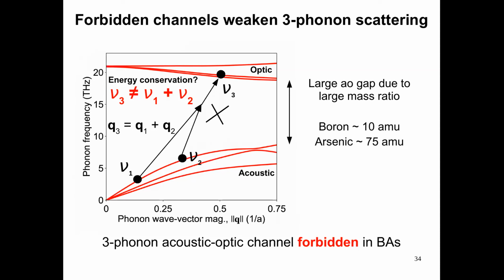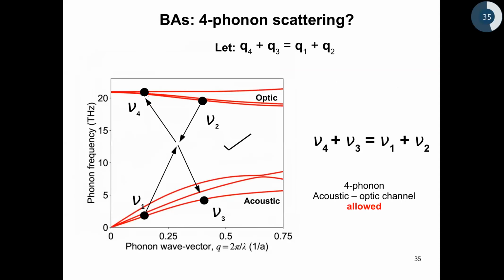So naturally, a question will arise at this point: what about higher order scattering involving more than 3 phonons? So clearly, you can see from this picture that if you add 1 more phonon to the mix, you can satisfy both momentum and energy conservation simultaneously. So at least from the constraints perspective, 4 phonons acoustic optic channel is allowed. But typically, scattering events involving large number of phonons is typically a higher order process in perturbation theory, and the strength of these higher order processes are expected to be weak.